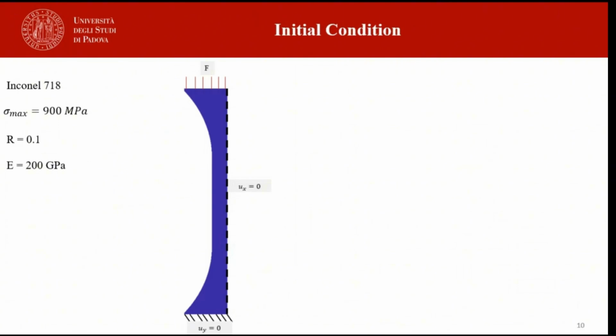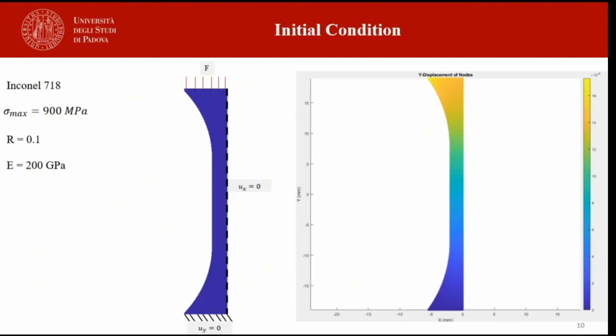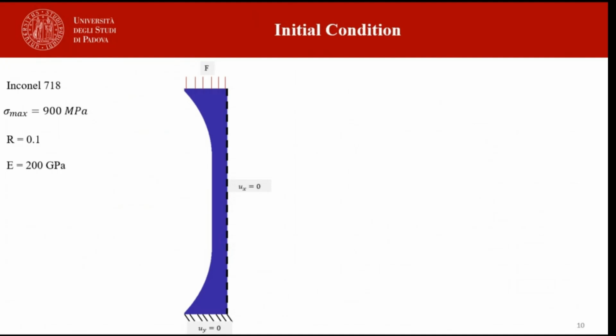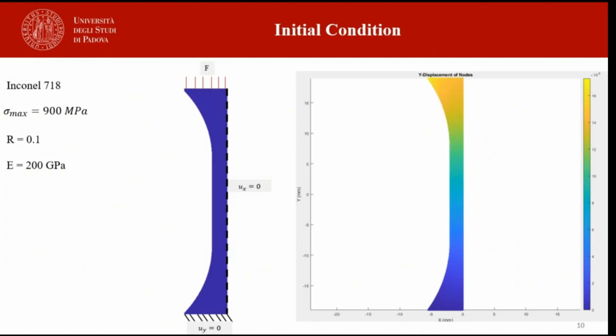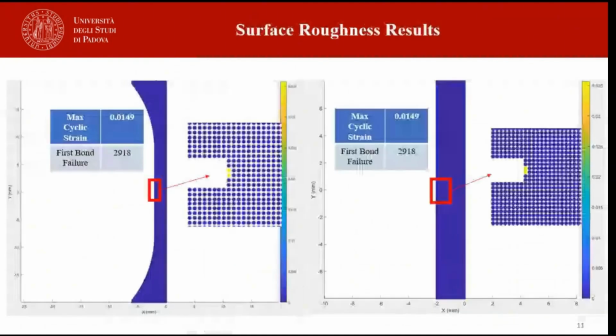Because of the geometric symmetry, we create half of the specimen to reduce the computational cost. We apply boundary conditions: fix the bottom nodes in the y direction, apply a symmetric boundary condition, and the upper nodes are subjected to cyclic loading. This graph illustrates the y displacement across the specimen, giving further insight into deformation behavior.